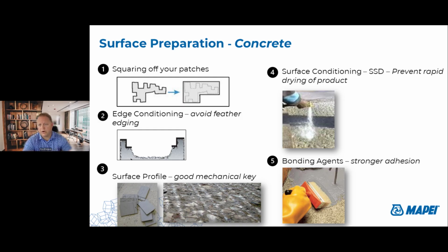specification or standard for how to reach this SSD, and it will really depend also on where in the country you are. If you're in Phoenix, close to where I'm at, in the summer, it's going to be very different trying to reach this than if you are in New York in the winter. I've heard some people say you can spray the surface down, and then you can go back with a leaf blower and try to blow out any pockets of water that accumulate in the pores there. I've even heard of others who'll take a piece of cardboard and put it where the people are using a leaf blower, and they'll see if any water is splashing up. And if it's minimal, then they go, okay, we reached this SSD condition.